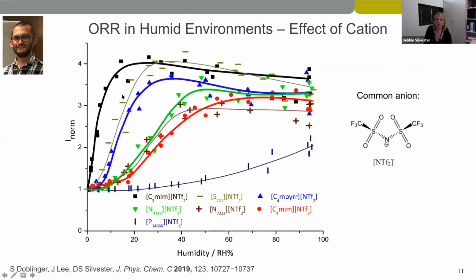But it's very different when we look at the cation. If we keep the anion constant with the NTF2, we have 8 different cations here. You can see that even in the very low humidity range, 0 to 20%, we have a very large response, a change in the current, even for 3 of the ionic liquids. If you take the black line, this is the C2 MIM NTF2, and we already have a roughly 4 times current response at less than 20% humidity.